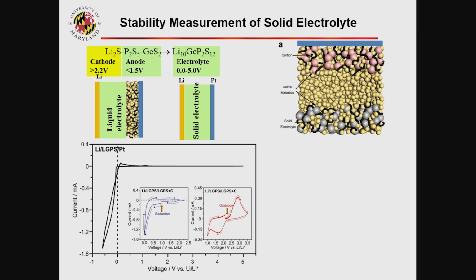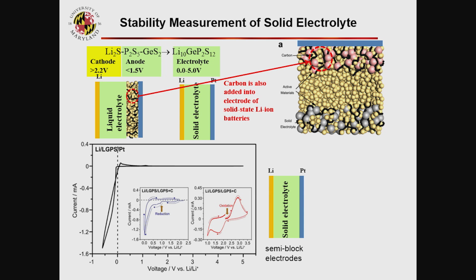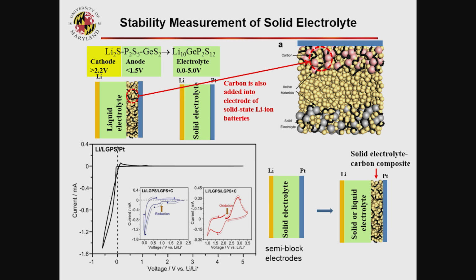So this confirms the problem when they published the paper, they used the traditional, this semi-block electrode. They cannot detect intrinsic true stability window. And then we just mentioned, since this structure is the same as we test, we think this is the right way to test the intrinsic stability of electrolytes. Then our suggestion is we need to change the method from semi-block to this technology. So we have to mix with carbon black to the electrolyte, and then we can get the intrinsic stability window.